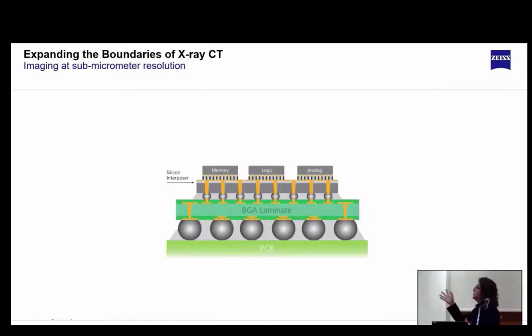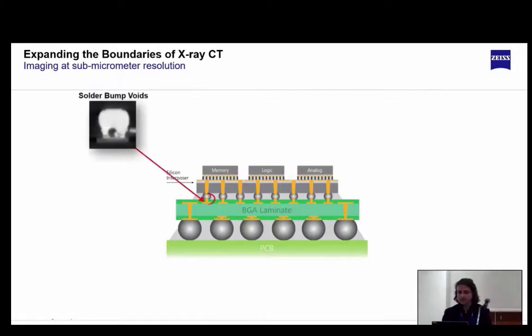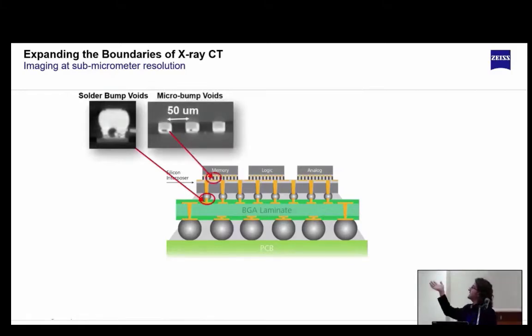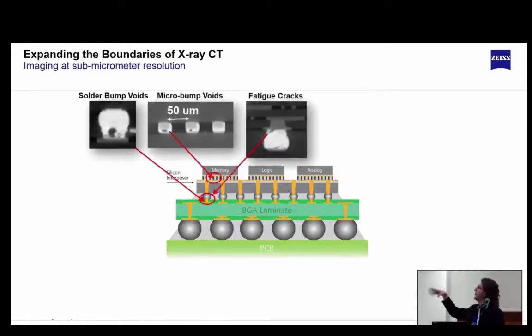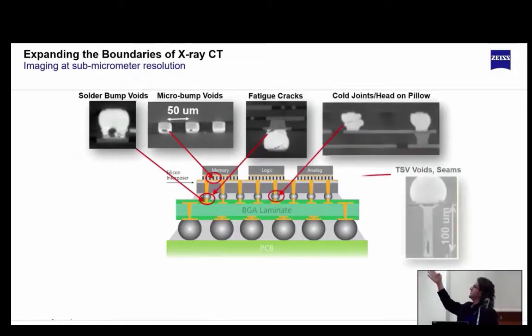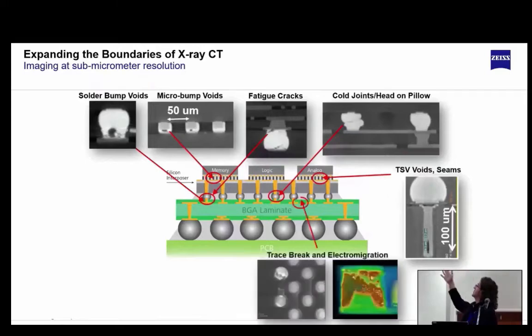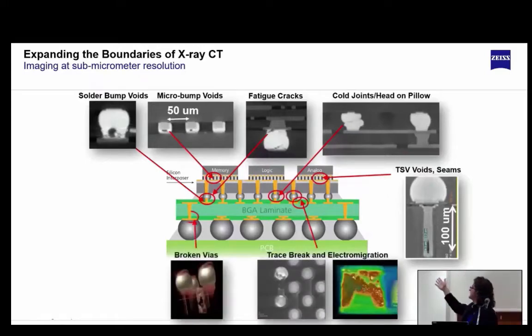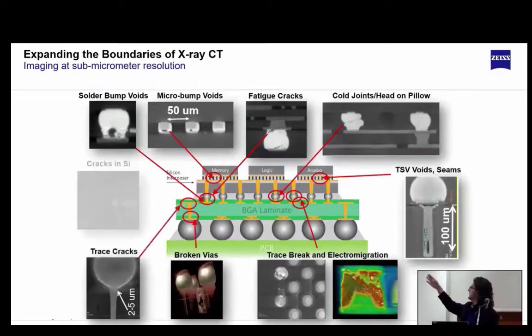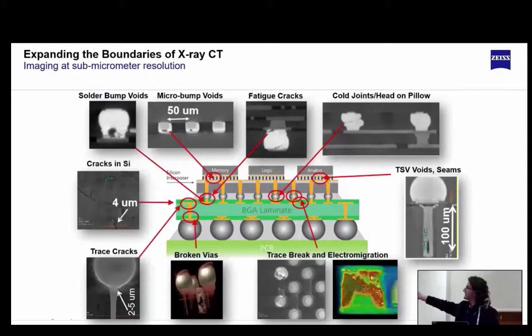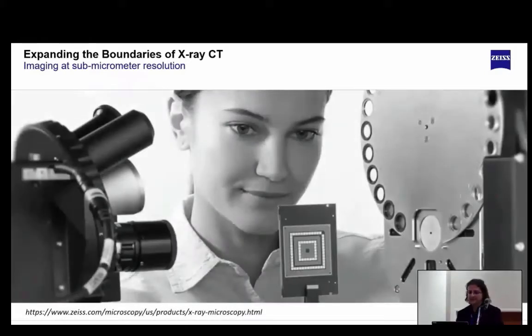Instead of simple projections, with 2D slices you can extract all kinds of information like you see in this PCB or BGA, where you can check for solder bump voids, micro bump voids, fatigue cracks, cold joints or head-on pillow, voids, electromigration, traces of any kind of defects, like you can see the broken vias, cracks, and micro cracks, and the silicon features of this electronic device. Again, this level of detail is only possible thanks to the optical magnification, keeping the full device in its full integrity. You don't have to slice the device.